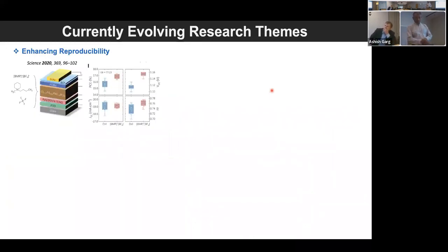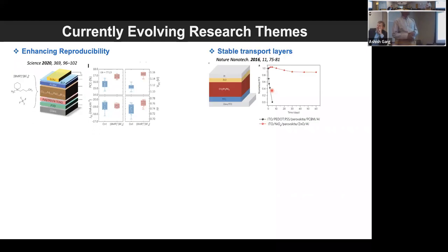So how do we solve these problems? Enhancing reproducibility is an issue which has affected almost everyone. So people have tried various methods, using different additives and so on, to improve the reproducibility of devices. Another is how to incorporate materials which are stable and low cost. For example, spiro-OMeTAD, which is the hole transporting layer, is known for its degradability as well as its high cost. So people have looked at inverted configurations, where we use solution processable oxides like nickel oxide and zinc oxide, which lead to higher stability of these devices. Not very stable at the moment, but still more stable as compared to those based on organic compounds.